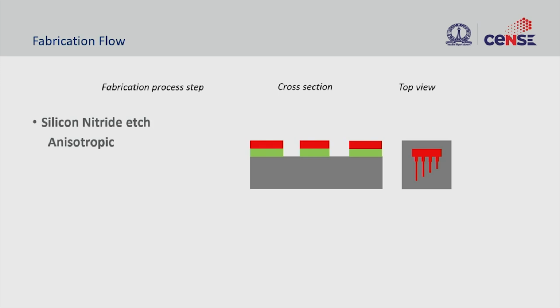The first step here is to anisotropically etch this nitride. And in order to make this cantilever, we have to remove the underlying silicon substrate. The silicon nitride etch is going to be done in an ICP RIE tool. The next step is removing the underlying silicon, which should be done in an isotropic manner. That means you want to remove all the silicon that is present underneath the nitride, so you don't want a directional etch. Here we want an isotropic etch, right? So how do we do this?